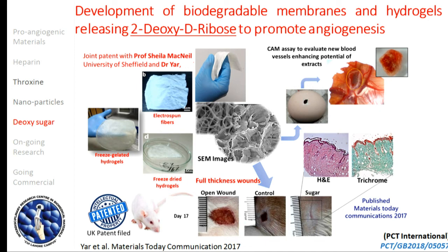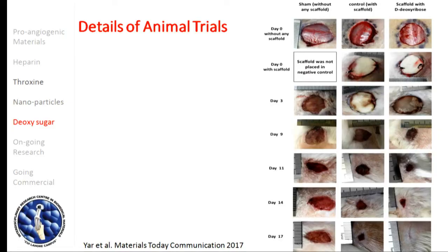And animal trials showed us that at day 17, in the case where we put this sugar-containing graft, the wound was closed very well. We have done the histology as well. In the histology, we can see that there is proper formation of epidermis and dermis and even hair follicles as well. So these are detailed animal trial slides.